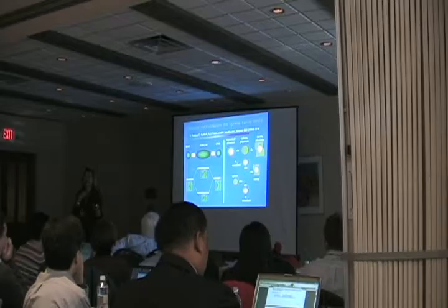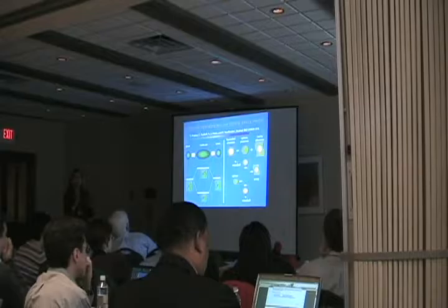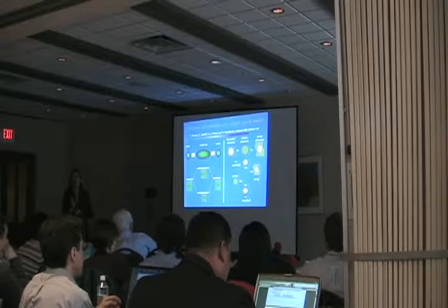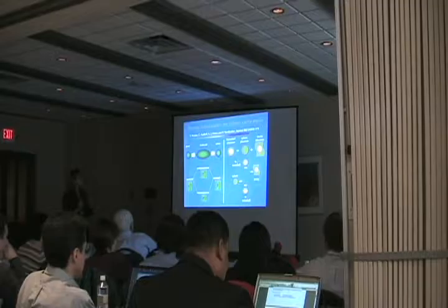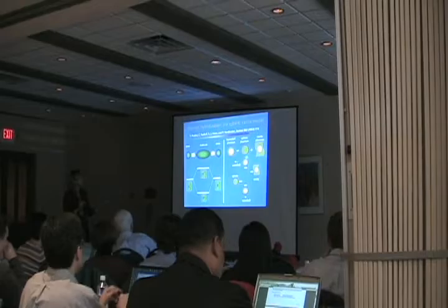and trying to understand why that's such a tunable plasmon led us to a very interesting idea, which is really a paradigm. And it's an observation. It's very powerful and important as far as I'm concerned for understanding anything having to do with plasmons, localized or otherwise. And the basic idea is that collective electronic resonances mix and hybridize exactly the same way that wave functions do in simple atoms and molecules.